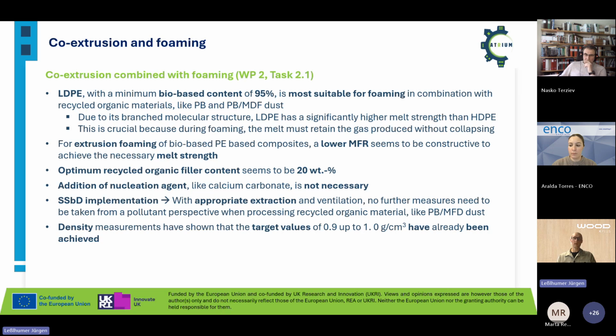And we saw in many test series that the optimum recycled organic filler content seems to be 20%, and we do not have to add nucleating agents like calcium carbonate. During the first year of the project, we also had a look at the safety aspects, or the safety at work. We saw during measurements that with appropriate extraction and ventilation, no further measures need to be taken from an occupational safety perspective when processing recycled organic materials like particle boards or medium density fiberboard dust. And we have already reached a key performance indicator of a density between 0.9 and up to 1 gram per cubic centimeter.